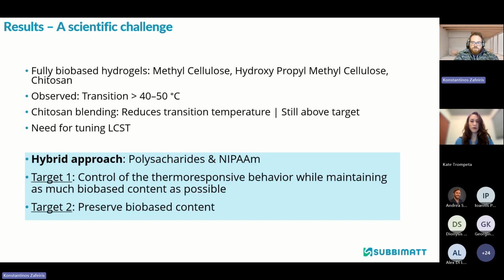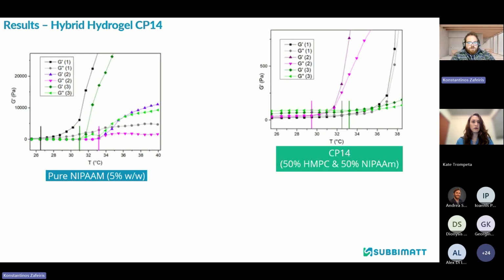So to address this, we followed, let's say, a hybrid approach, and we kept the polysaccharides in our recipes. However, we added a synthetic ingredient, as Faye already mentioned. So we had a polysaccharide backbone consisting of cellulose derivatives and hydrogel, and combined it with isopropyl acrylamide. The goal was to achieve precise control of the thermoresponsive behavior while maintaining as much bio-based content as possible. And our compromise was a very good analogy, 50% bio-based content and 50% synthetic.